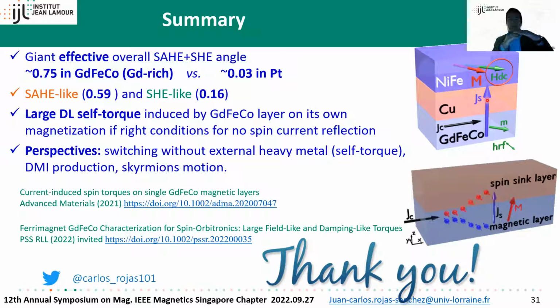When we look for thinner and thinner films, it becomes a bit challenging. And we have found out that when we have platinum on the bottom, it could help, but platinum also affects the compensation point, either in temperature or in concentration. However, and that is interesting, if we use copper, the perpendicular anisotropy and the compensation point are affected not only by the buffer layer, the layer in the bottom, but also by the top layer or capping layer.